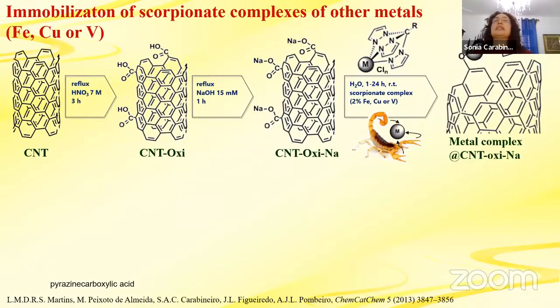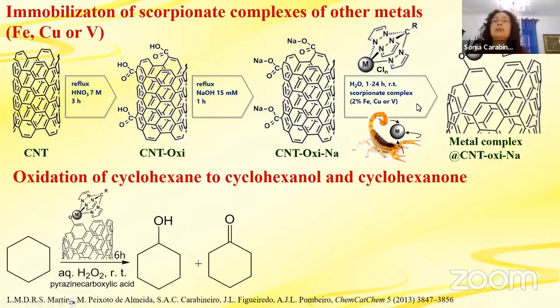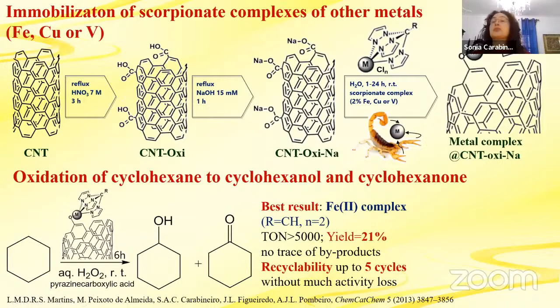Also, we tested immobilization of scorpionate complexes of other metals. So here, iron, copper, and vanadium, for example. And we also could obtain good yields in 6 hours, but they needed acid. The ones on gold did not need. The best result was obtained with an iron 2 complex.